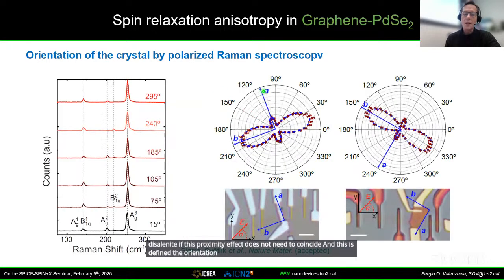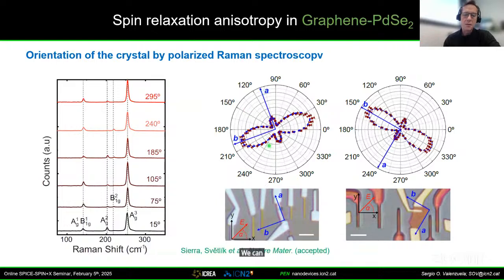If the component is in this direction, you will have that the longest spin lifetime is along this arbitrary axis that I'm selecting. This is the axis that defines the crystalline orientation of the palladium diselenide. This proximity effect does not need to coincide, and the orientation is defined by the angle theta. We can determine the orientation of a crystal in different devices by doing Raman. This material is very anisotropic for Raman. The A-axis in this device is oriented here. In this device, it's oriented there. You can see it from the symmetry of the Raman.